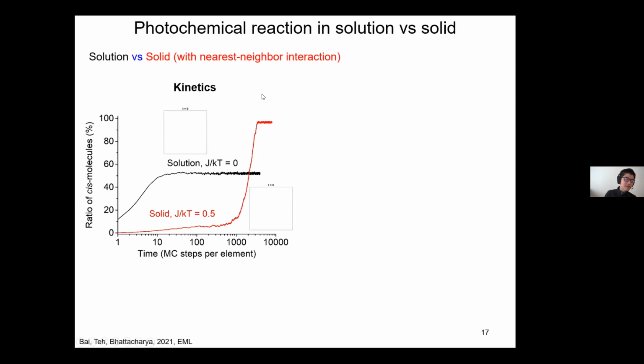Now I shine a light of a constant intensity and I just wait, okay? So this is a solution where I don't have any interaction or the interaction is very small. You can see very quickly it reaches equilibrium, and this is really just the first order kinetics. Nothing special, nothing surprising. In the solid, however, it becomes pretty much slower, and I will have random islands, but later on I will have some nucleation and growth. So let me first fast forward this. You can see clearly you have a nucleation growth. So, and recording this, you can have a very sigmoidal-like curve or S-shaped curve.